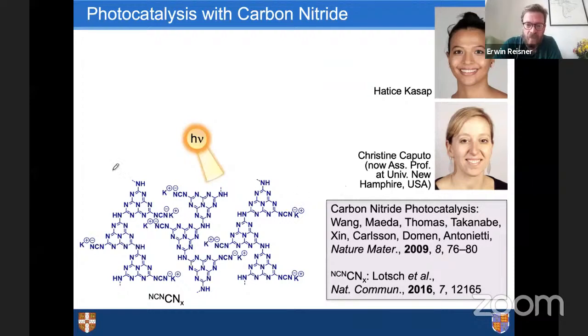So I will just briefly say that this is an organic semiconductor-like material with really pioneering work, in fact, by Markus Antonietti, and especially the seminal paper here in collaboration with Katsunori Domen really put carbon nitrides on the map as a sustainable photocatalyst. And it had already been developed for organic systems. Then with this nice paper, it became relevant for water splitting. And now it seems to be all over the place in the organic literature as a real replacement for iridium or ruthenium dyes for sustainable chemistry. And in the system we use a particular variant of this carbon nitride with this NCN cyanamide functionality that was first reported here by Bettina Lotsch. And this was work by Hatice Kasap and Christine Caputo.